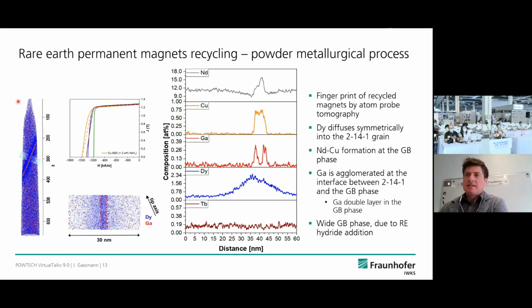In this case, the sample is shown here. So basically the sample is in the nanometer scale. So here we have about 600 nanometers. So it's a very local, sensitive, atomic resolution detection method. Basically, one can measure the composition on the atomic scale. So for us, the most interesting part is the region of the grain boundary phase, which is also shown here, and here in detail for different kinds of elements.